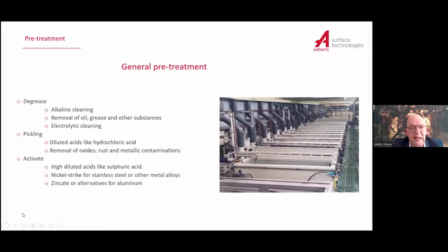When you start plating, on the left side of the slide, you see what you need. First, you have to take off all the oil and grease. By grinding and milling and all that kind of stuff, which you do to the materials, you get a lot of oil and fat on your parts, and you have to clean that. Normally that's done with alkaline cleaning, which takes off the oil and the grease. You do a deep cleaning, done electrolytically, where gas develops on the parts and cleans out all the pores, and so you clean your parts of the oil and the grease.